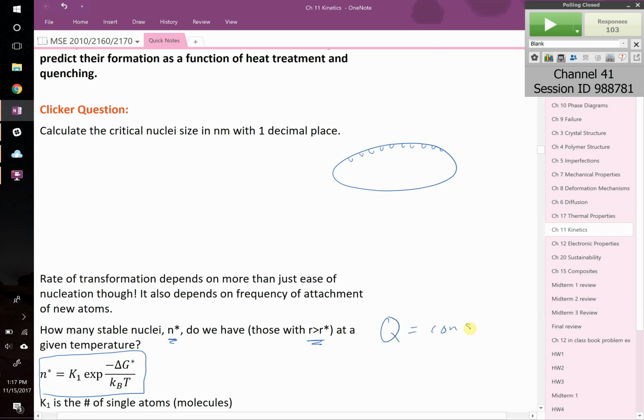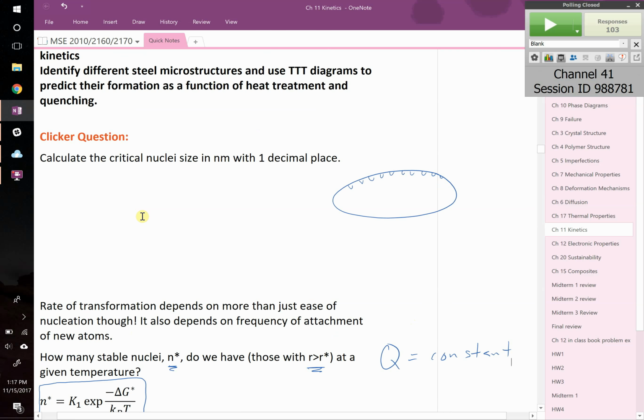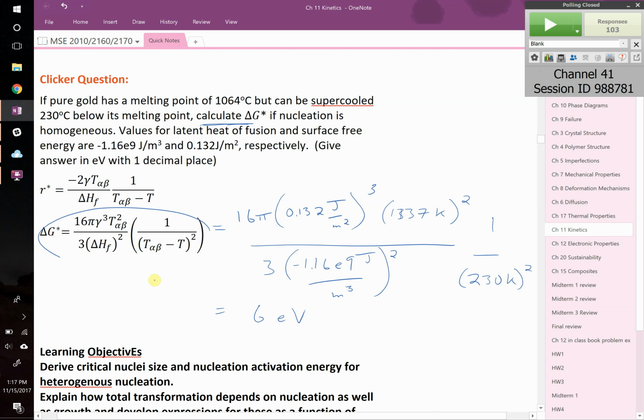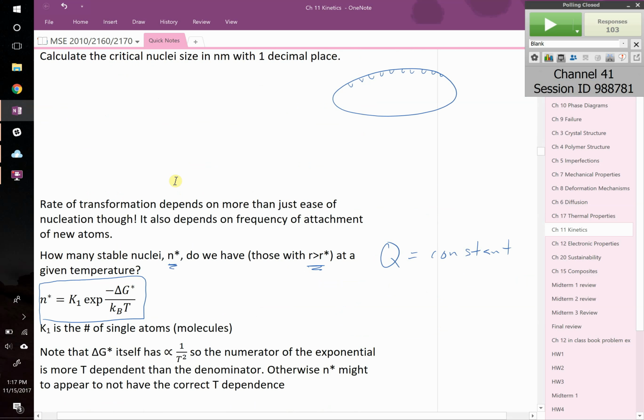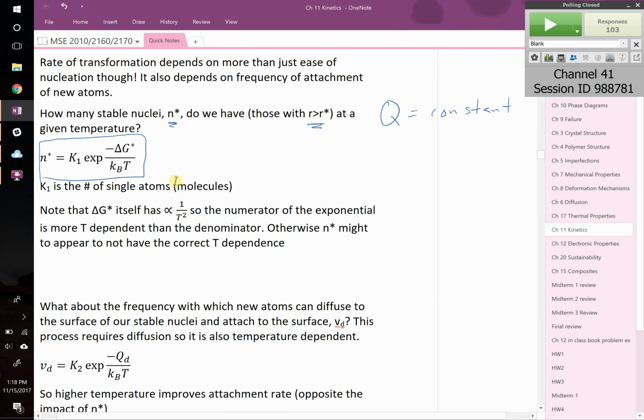Q equals constant. So if it's activation energy for vacancy formation or for diffusion or whatever, that was always a constant, right? At least over some temperature range. What do we know about delta G star? Is it constant with respect to temperature? Definitely not. In fact, we know how it depends on temperature, right? As you change temperature, the further below its melting point or whatever the transition temperature is that you go, it's changing. So this isn't exactly like the thermally activated processes we've come to know and love in this class. This has to be modified. This has a stronger temperature dependence, because delta G star itself has a 1 over T squared in it, right?